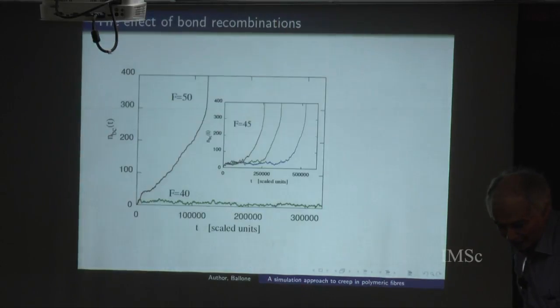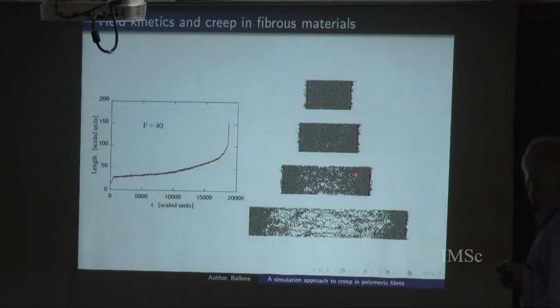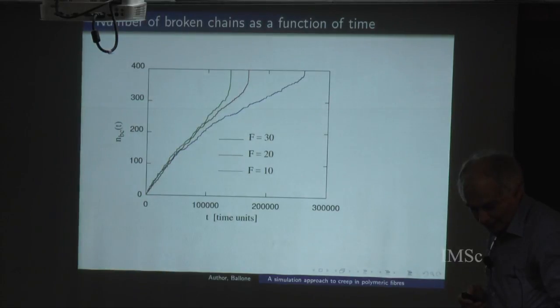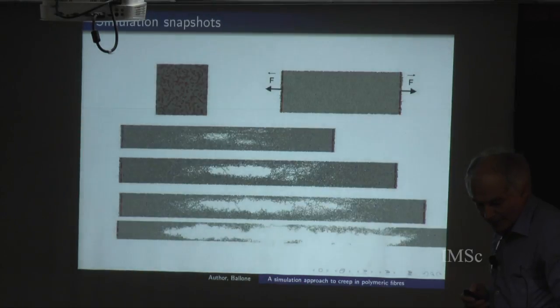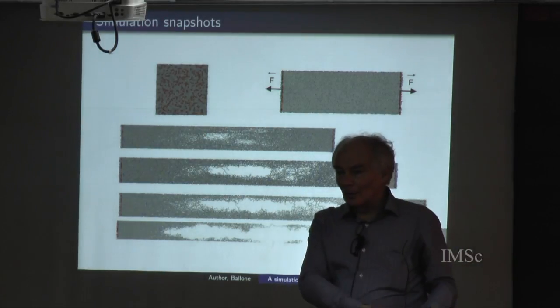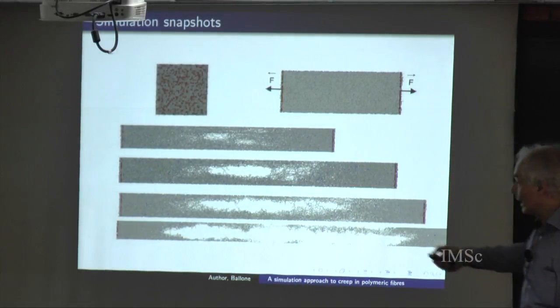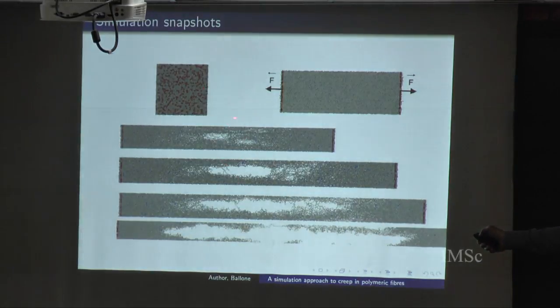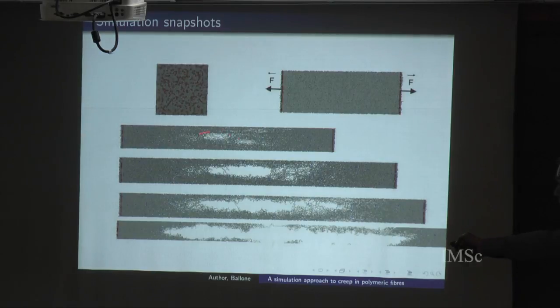So if you remember what we had at this point, we had chain breaking essentially everywhere at random, without any structure or pattern where breakings took place. Now you immediately notice a difference. That is what has been discussed yesterday. There is a nucleation of a bubble. So we separate the two phases, the particle phase and the vapor. And since this is a simulation with periodic boundary conditions, it has to take place somewhere in the system, and it takes place in a localized way, as a nucleation event. And then it grows until it breaks.